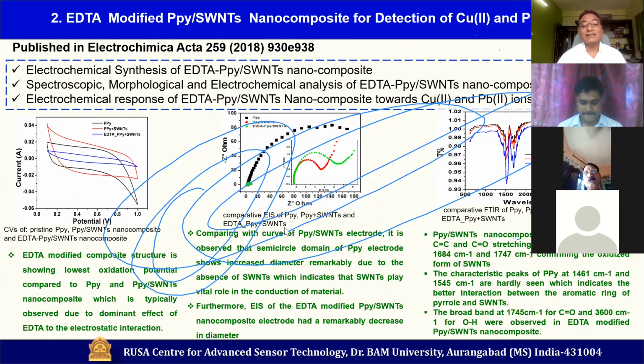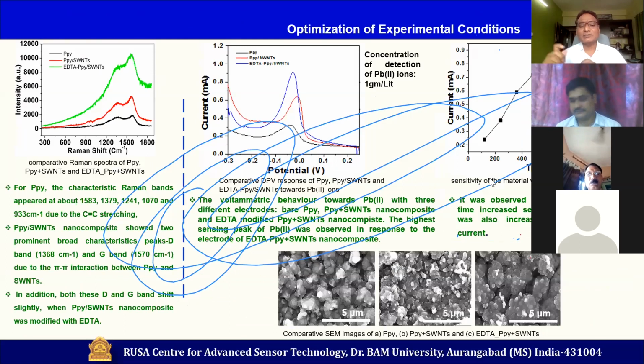Similarly, we went ahead and did EIS also, and in EIS studies also, we could get the significant discrimination in all these three different devices, and same thing is true with FTIR as well. So this characterization was done just to understand whether those functional groups are there, and whether there is a clear-cut distinction between bare, composite, and modified devices, right? And same thing, we went ahead and did Raman spectra as well. You can see there is a slight shift in D and G, both the bands, whenever we modified this nanostructure with EDTA. And then we went ahead and did this voltammetric behavior for detection of lead.